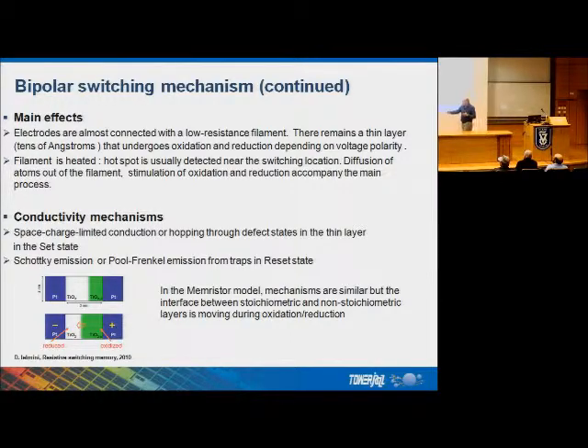So moving back to the memristor model, actually the memristor model is very similar to what I mentioned. Also, titanium oxide and non-stoichiometric titanium oxide, like in the designs of all the memories that I mentioned, that maybe are not considered as memristors, but simply as for storage of 0, 1. In case of memristors, one of the main models is the moving of the interface between the stoichiometric and non-stoichiometric titanium oxide, so that the space is more narrow near the minus electrode in the reduced case compared with the oxidized case. So this is the switching, moving of the interface, different resistance in the memristor. From the point of view of memories, it is a very similar mechanism.